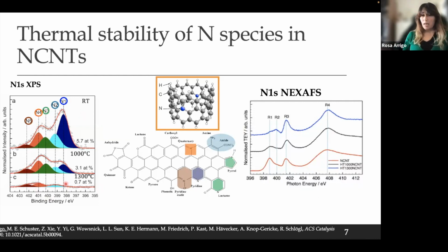Now, with these two systems, we can see whether there is a direct coordination between the metal center and the nitrogen. But XPS is not the right method to do that, because here you would see a shift, and of course, the shift within this very broad peak will be difficult to evaluate. However, absorption spectroscopy at the nitrogen K edge, so from the 1s to the LUMO, the lowest unoccupied molecular orbital, will be the best method to identify metal-support interaction.